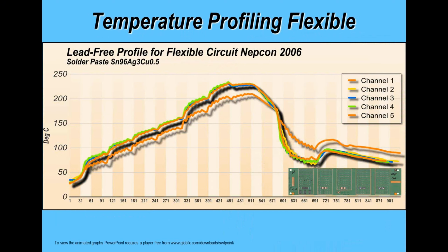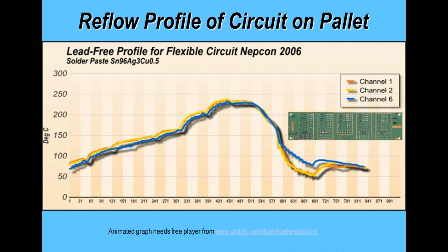I just included a couple of graphs in here just to show you the impact. So this was a production process we were running in 2006 when we were introducing lead-free to the industry. And you can see here there is a delta T between these temperature curves, pretty much all the way through, but particularly on reflow. Now, when I modified the pallet, this is the impact. So I was able to successfully reflow solder the SAC alloy, but I had a much smaller delta T. Now, again, this may be obvious to you who are sitting on the webinar this morning, but again, it's something to always consider. What impact will other things have on your profile?